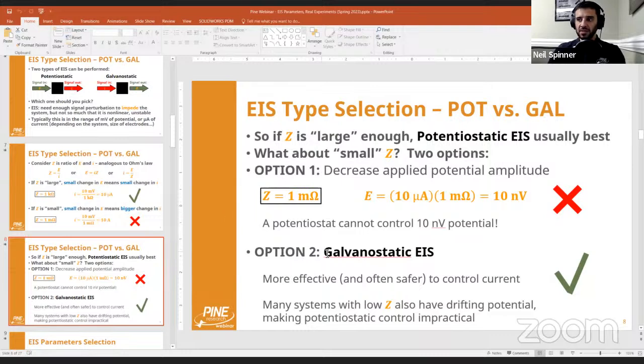So I almost never say this in a webinar as official advice, and I'm not necessarily giving you official advice right now, but galvanostatic impedance is often a lot better, from the perspective that there's something about the practicality of the control galvanostatically that's a little better. It's just dangerous because the potential can whip around and then you can have bad results. So I don't often recommend that you jump to galvanostatic impedance right away, especially if you're doing aqueous phase stuff, even non-aqueous phase stuff. You probably want to start with potentiostatic. It's just safer because you might inadvertently pick too big of a current and then you're swinging up 500 millivolts, a volt or something. And you do that, you're going to really damage your components. You might irreparably damage your electrodes. And that's going to really cause a bad day in the lab.